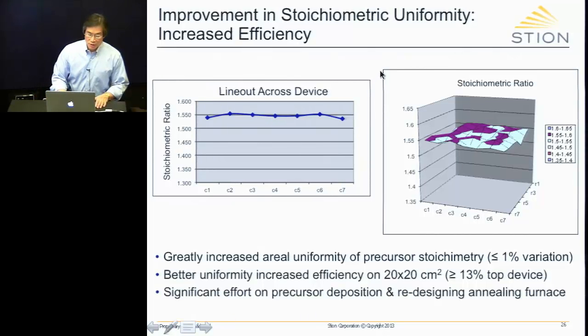So the stoichiometric uniformity: as mentioned, these are chalcopyrites, and so we put down metal precursors. This is a 3-dimensional plot of the stoichiometry in the XY plane. This is the stoichiometric ratio, and you see it's reasonably flat. Here's a line out across there. What we've been able to do is increase the uniformity to less than 1% variation over that area.